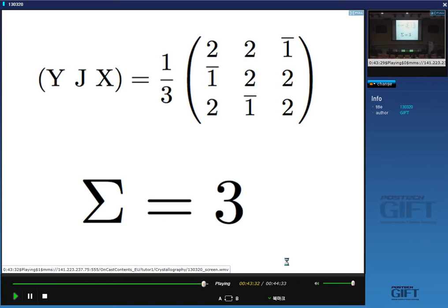Now the sigma value concept is very important because you have very easy tools to work out sigma values. Your computer programs will give you those values, and you know that when you have small sigma values, in other words a large fraction of the lattice points are coincident, it will be a low energy boundary and its properties will be totally different from a high sigma value boundary, because diffusion coefficients, interfacial energy, the strength of the boundary, everything will depend on the structure of the boundary.